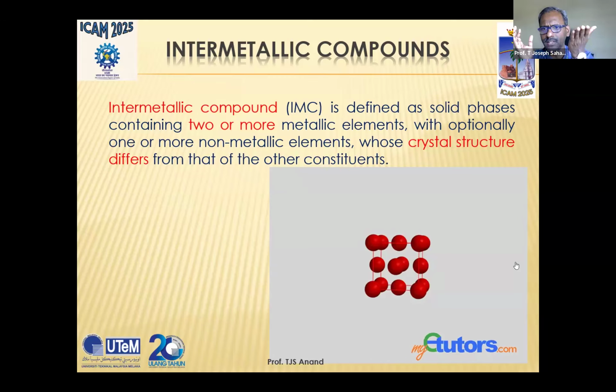I am taking one piece of aluminium, one piece of nickel, and I want to merge them together, either by casting or welding. There are many methods. Here normally we use casting. So we completely merge them together, going up to the melting temperature to make it an alloy. And that alloy I can still call an intermetallic compound because, if you remember, I said nickel has the melting temperature of 1455 degrees centigrade, aluminium has 660. When I am combining them together, it now becomes a nickel aluminum alloy, NiAl alloy.